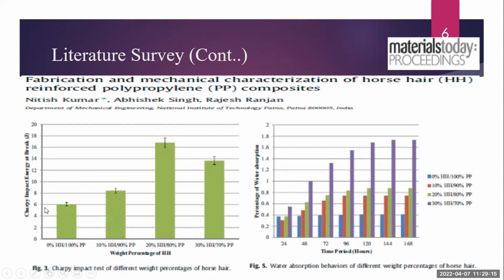Also, they used these samples to test the impact strength with the help of this impact test, and they found a very interesting result again. The mixing of 20 weight percent of horsehair with 80 weight percent of polypropylene again gives the best result compared to the other compositions.